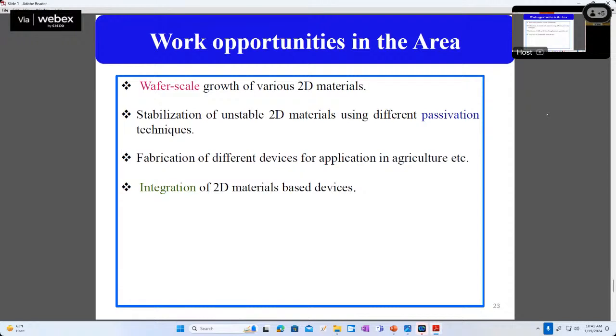And then fabrication of different devices, as we discussed, agriculture. There are other applications also, like photonics. People are working in this one, okay, and spintronics, all these fancy things people are doing using these materials. For memory devices also people are using these materials, because you may have heard about short channel effect in MOSFET. Okay, short channel effect is more in 3D materials, but if you use 2D materials, their layer thickness is very small. So short channel effect is less even if the device dimension is shrunk to 4 to 5 nanometers. Okay, so short channel effects are less if you fabricate a MOS using these materials.